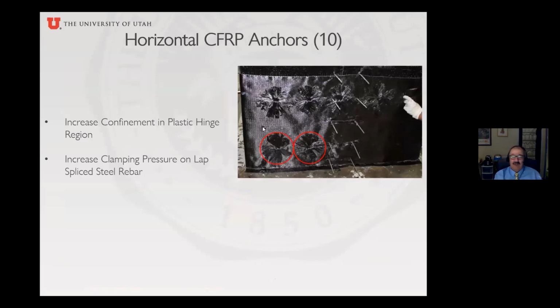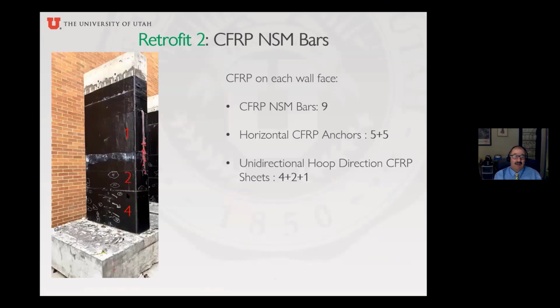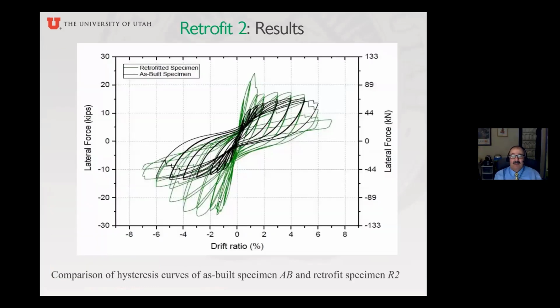Here again, you see the anchors, the transverse anchors that we talked about. And here you see the 4-2-1 layers for confinement. So here is the result. You can see that this specimen again went almost to 25 kips, but unfortunately this one again at around 2%, we had one of those near surface mounted rods pull out of the hole because the resin that we put in there was not packed correctly.